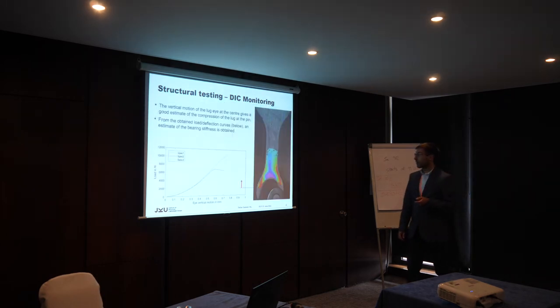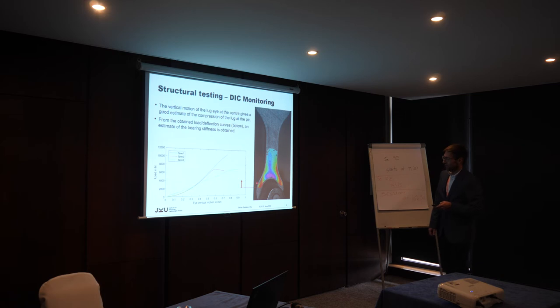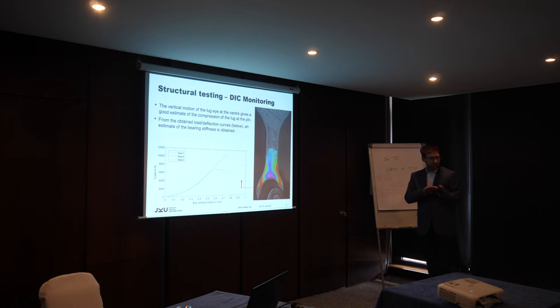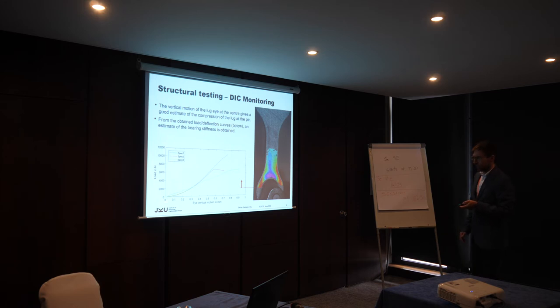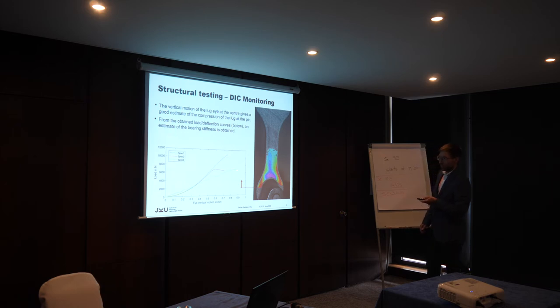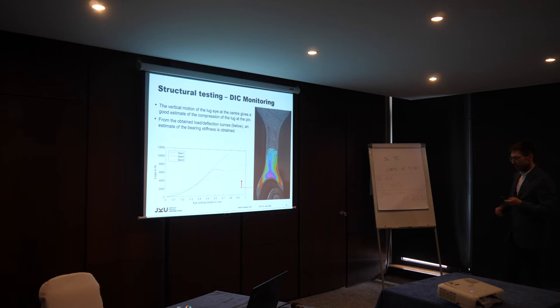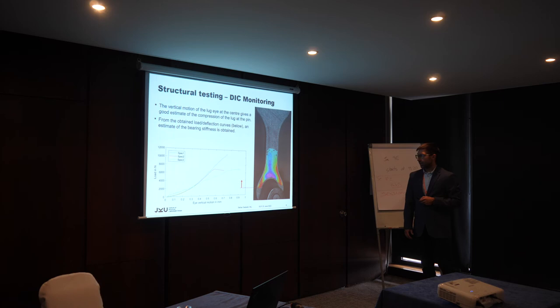One way to get more detail on this hypothesis was to look at the bearing stiffness of our lug. By looking at the vertical displacement of a point at the mid-section we can get a representation of bearing stiffness — the elastic imprint from the pin. Initially all specimens look fairly similar, which is expected since it's a matrix mode. But then specimen one goes to a higher stiffness, while specimens two and three show a softening behavior, potentially explained by broken layers reducing the contact area under pressure.